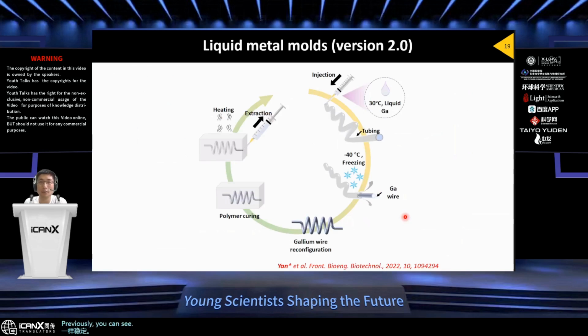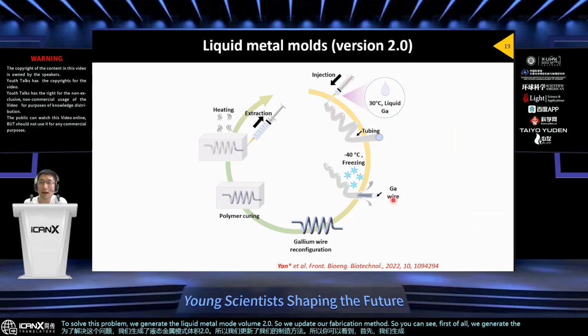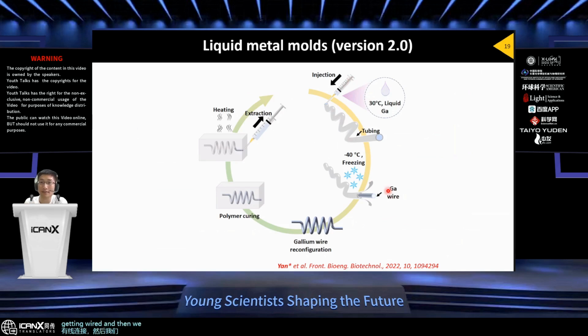Previously, you can see we can generate the soft microfluidics, but all the devices are based on the copper surface. So to solve this problem, we generated the liquid metal mold 2.0. We updated our fabrication method. First of all, we generate the Gallium wire, and then we reconstruct the wire into a freestanding structure, and then we use the elastomer to encapsulate the wire, and then we remove the metal after heating. So this is the freestanding 3D channel.